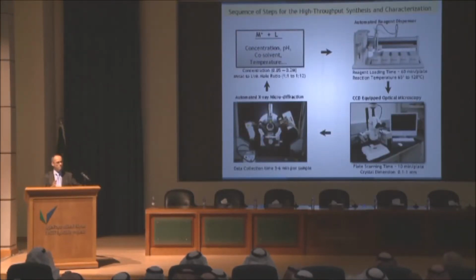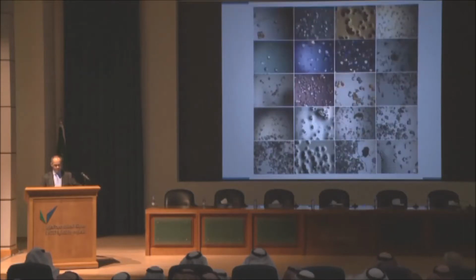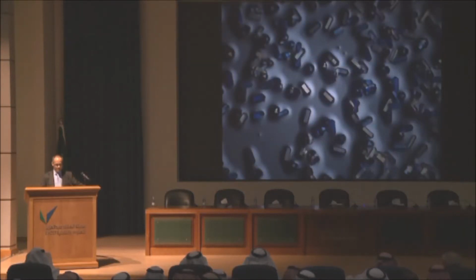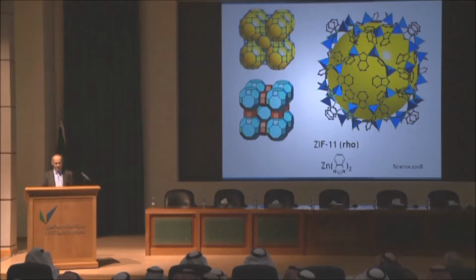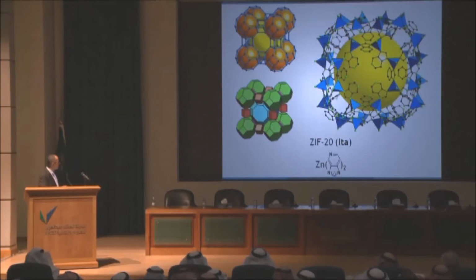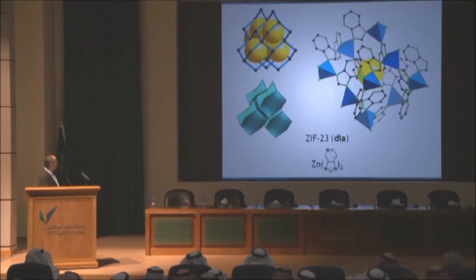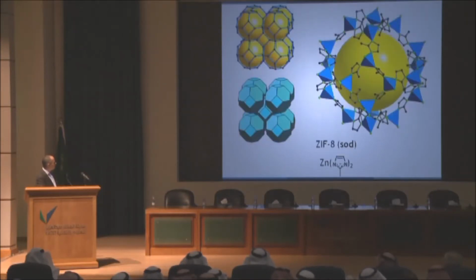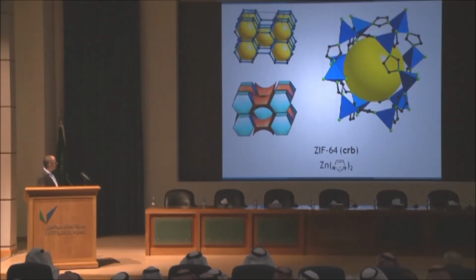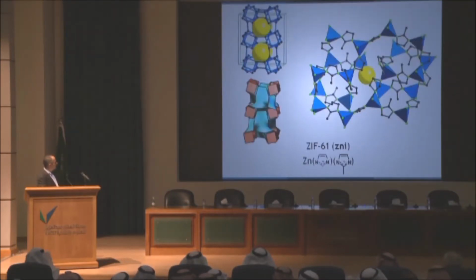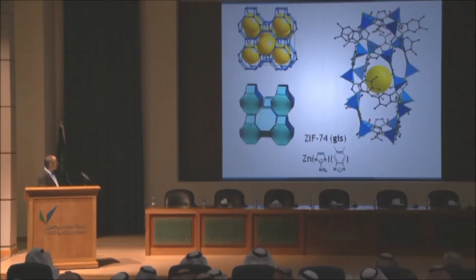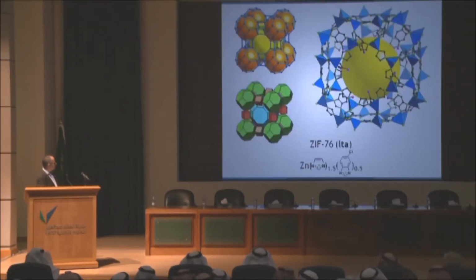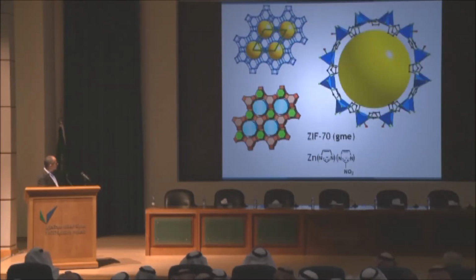And so we did the high throughput synthesis to search for all the possible structures, and again, my love for crystals. Here are some of the crystals that you see in those wells. And in just one experiment involving about 10,000 reactions, we discovered 25 different structures. And these are, I'm going to just show a movie of them. You can see these are all based on zeolite type structures that are made from metal organic. We can make them from almost any kind of link, polar, non-polar, mixed links. The metal can change from zinc to cobalt and others at this time. We made some of the most important zeolites as metal organics, as you can see here.